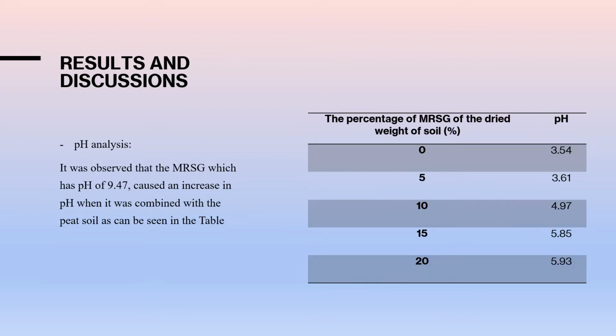pH analysis. The MRSG, which has a pH of 9.47, making it extremely alkaline, caused an increase in the pH of the peat when it was combined. As shown in the table, the pH for peat without MRSG is 3.54, but it increased up to 5.93 with a 20% content of MRSG.